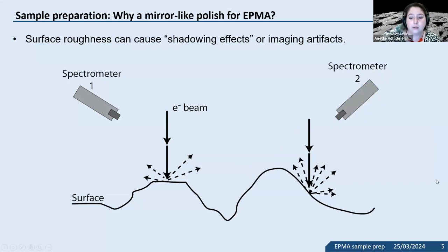If you look at something in secondary electron images, but also backscatter, you can have artifacts that have nothing to do with a difference in composition. And even more, these artifacts tend to be directional, depending on where your spectrometer is looking at it. Only when you're better than 1 micron, because of the wavelengths of the X-rays and everything else, do you not have these kinds of problems.